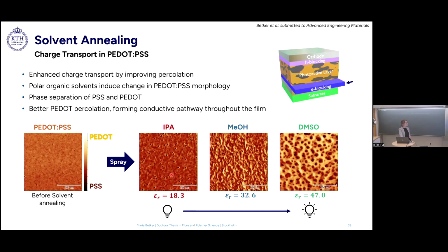So let's start with the isopropanol. We see that here we have a formation of darker spots, which represents the PSS, but all in all, the films look quite similar still, right? When we then go to the methanol, we see now the formation of these yellow pathways, which is the conductive PEDOT, which enhances the percolation, so enhances the conductivity. And then finally, for the DMSO, we have the most drastic change. Here we have a well-percolated network of PEDOT, which explains why DMSO was the most effective solvent in this experiment.